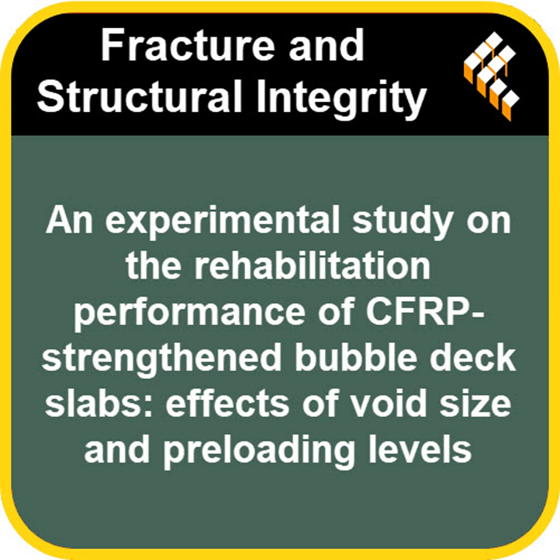So not only did they regain strength, potentially exceeding the original bubble slab, but they also became much stiffer too, less sag. Precisely. They became more rigid. For a specific example, take the 50 mm void slab that was pre-damaged to 50%, that specimen SB550. It recovered approximately 98.5% of the solid control slab's load capacity. Almost back to the solid slab level. Almost fully restored. And its deflection was reduced by around 22.5% compared to the unreinforced bubble slab.